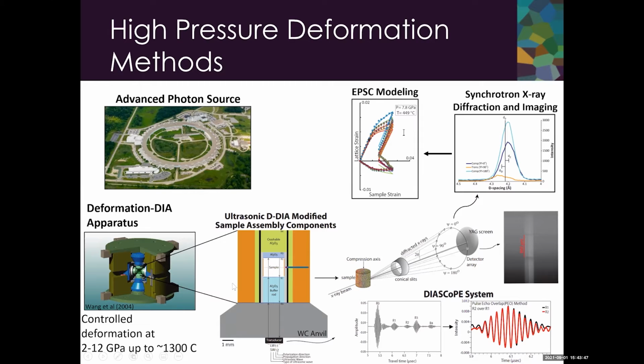This is a schematic of the hybrid D-dia ultrasonic cell assembly with our sample of polycrystalline material in the center. Recently, we've added the use of ultrasonics, incorporating the diascope system to monitor our samples while we're deforming, allowing us to obtain the travel times within our sample. So using synchrotron white X-rays, we can also measure the length of our sample during deformation, and we can measure the lattice spacings within the sample with an array of energy dispersive detectors. We can then interpret our diffraction data using elastic plastic self-consistent modeling.